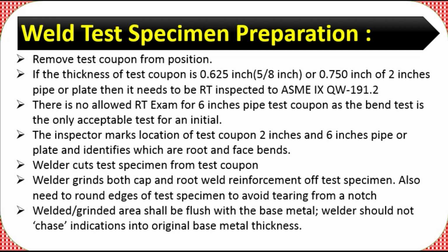If it is 2-inch pipe of this particular thickness, there is no bend test allowed; RT exam is required. For 6-inch pipe test coupons, the bend test is the only acceptable test for initial qualification, because on 2-inch pipe you cannot do the bend test, only the RT. You have to do the RT test to qualify that particular weld. If it is a 6-inch test, you can do the face bend test and root bend test as per the requirement. There is no RT exam allowed for 6 inches. For 6 inches only the bend test is acceptable.